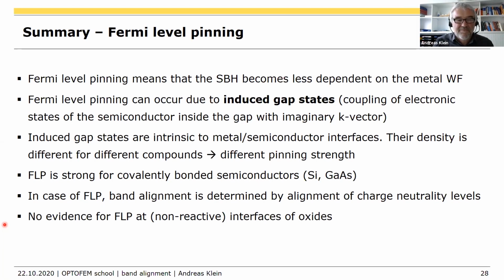So one has to look more into the details in order to get this. This is not just one charge neutrality level and the Fermi level is always there. So that means also the details of the wave functions of the metal. As I say, the induced gap states are caused by the coupling of the wave function of the metal with the decaying wave function in the semiconductor. If you change your metal, for example, by changing the orientation or by changing how you put this metal on top, the coupling will be different. And that means it will give you a different density of interface states. It's a very detailed structural thing. There was an extensive, very long review paper by Tung, T-U-N-G, which explains these kinds of things.